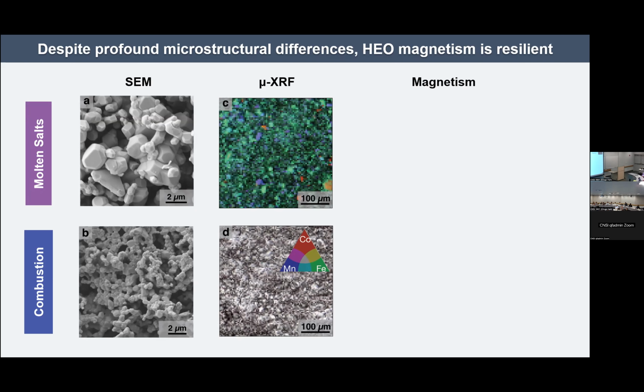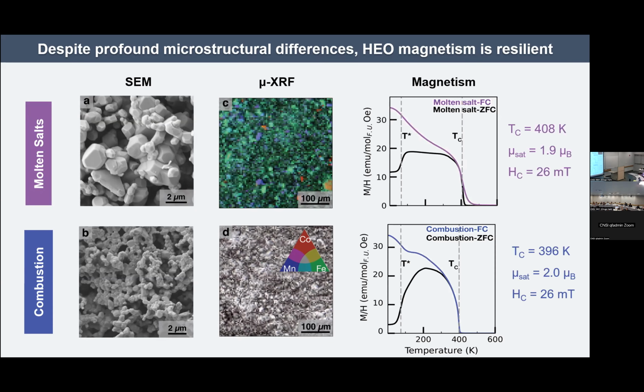So then the question that we were interested to know is, what effect do these microstructural differences have on the magnetism? We would expect that being iron-rich and inhomogeneous and having very different grain morphologies, these in general are things that will lead to differences in bulk properties. And what we have been astonished to find is not just across these 2 samples, but across all 5 samples produced by very different synthetic methods, the magnetism is very resilient.